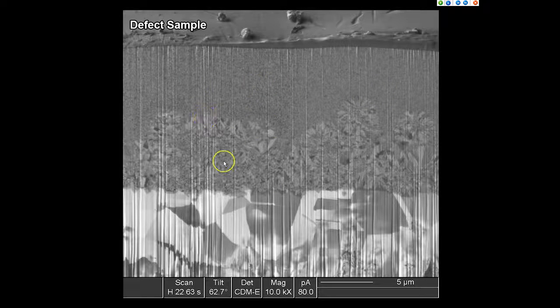And again, this would not have shown up in a standard mechanical section with SEM. You would not have seen the difference in those two nickel layers because their composition is the same, even though it's their grain structure that's different in this case. And furthermore, because of the high polish, you can see there's small little triangular cutouts in the substrate where it looks like the substrate was etched, which probably gives some indication of the chemistry that occurred that led to the formation of this defect in the first place.